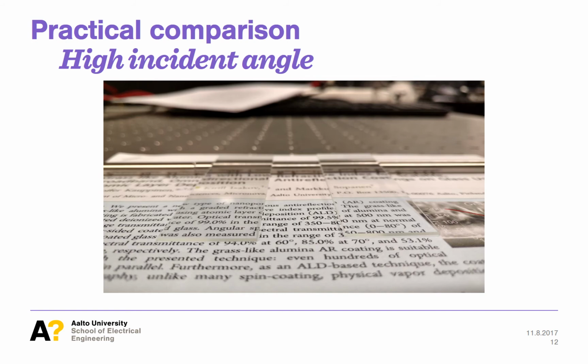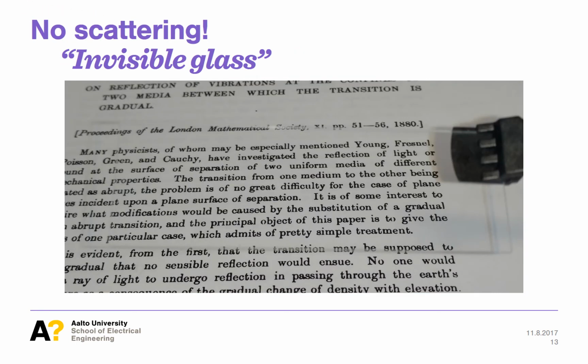The difference is even more apparent at high incident angles. Mostly, distortions caused by refraction give away the coated glass. At the same time, bare glass has a stronger gray color and reflects glare from lamps. It is vivid from this photo that coated glass is almost invisible. You can only notice the edges of the glass piece. This also demonstrates that there is no scattering of the transmitted light with grass-like alumina.